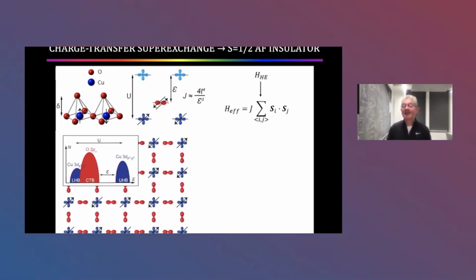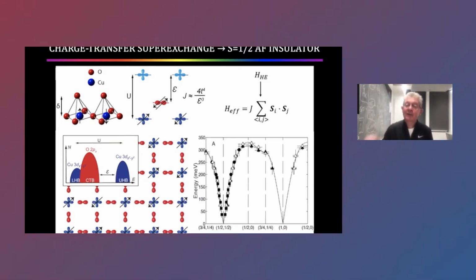It's an antiferromagnet. This antiferromagnet has to have the band structure of CuO2. So it has to have a lower Hubbard band, 3d9, upper Hubbard band, 3d10. It has to have the 2p6 band in between and the charge transfer separation epsilon. But otherwise, the spin-a-half electrons should form, in theory, a spin-a-half square lattice antiferromagnetic insulator, if superexchange theory is correct. And of course, that's exactly the state which occurs in the parent state of the cuprates. So what this tells us is that the superexchange picture is correct for the undoped compound.